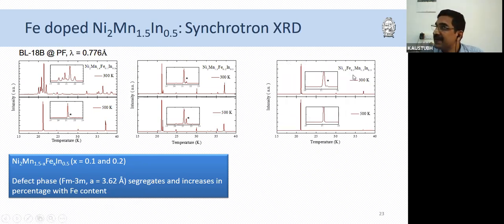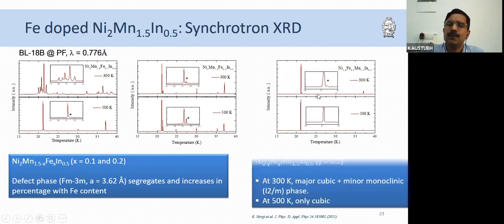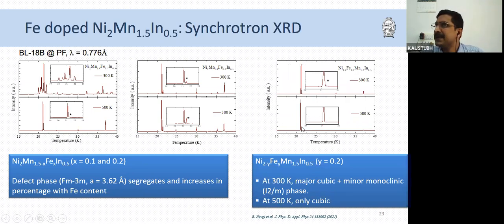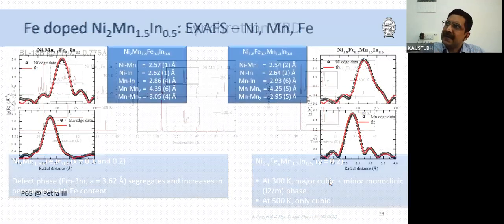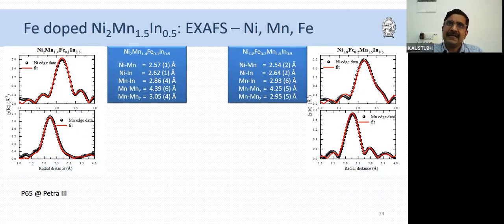In the case of NiFe, which was cubic in the lab, we could identify a small impurity monoclinic phase, I2/m, which disappeared also at 500 Kelvin. So therefore, there was a small martensitic impurity phase which disappeared at high temperature. So then we did EXAFS. We did EXAFS at the manganese K edge and nickel K edge, and these could be fitted exactly as in the case of the parent material. Everything was perfectly fine.